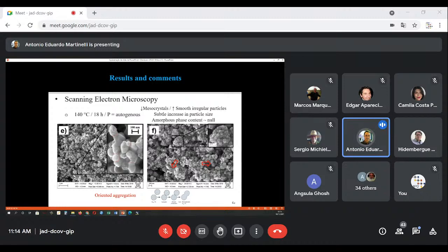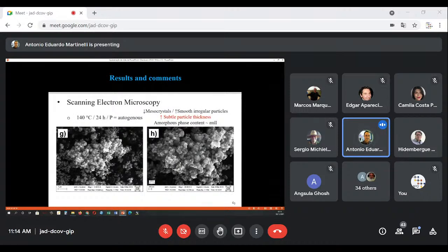This is a real mapping. This is a real temperature and time mapping. And pressure, as we see in the next micrographs. So 140 degrees C, 24 hours, autogenous pressure. We now have lower contents of mesocrystal, higher contents of smooth irregular particles, an increase of particle thickness, and we don't have an amorphous phase anymore.